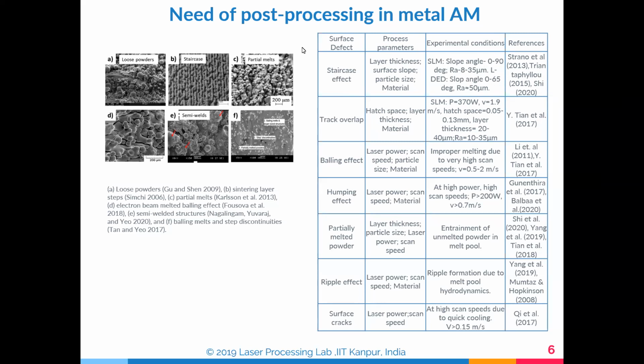So next is track overlap. In track overlap, what happens? The hatch spacing, the layer thickness, and the material are involved. Then you have the balling effect. Balling means you try to form something like balls. So the laser power, scanning speed, particle size, and materials all join together and form a balling effect. Then the humping effect. Balling is small things, humping is a large thing. The humping effect depends on laser power, scan speed, and material. They all join together and form it.